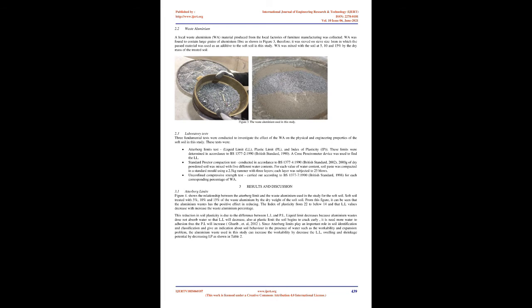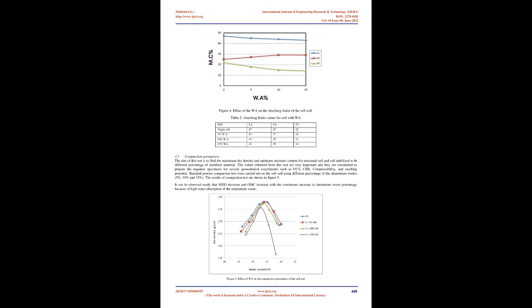Figure 4, effect of the WA on the Atterberg limits of the soft soil. Table 2. Atterberg limits values for soil with WA mix. LL, PL, PI. Virgin soil: 47, 25, 22. 5% WA: 45, 27, 18. 10% WA: 44, 29, 15. 15% WA: 43, 29, 14.